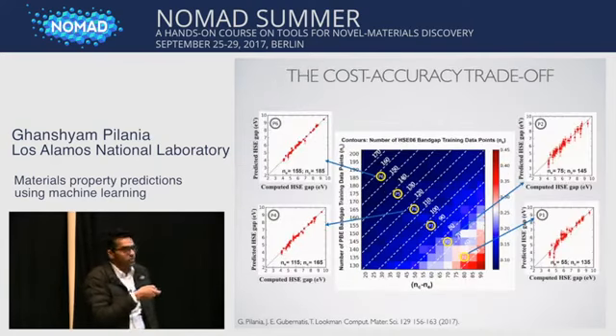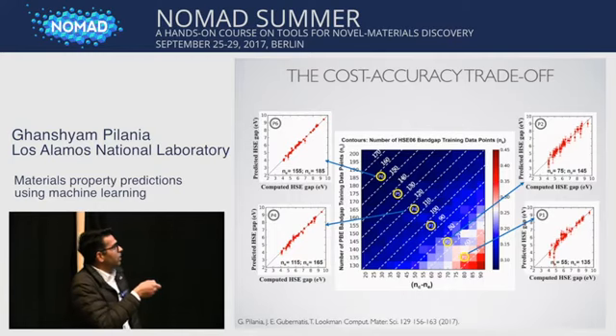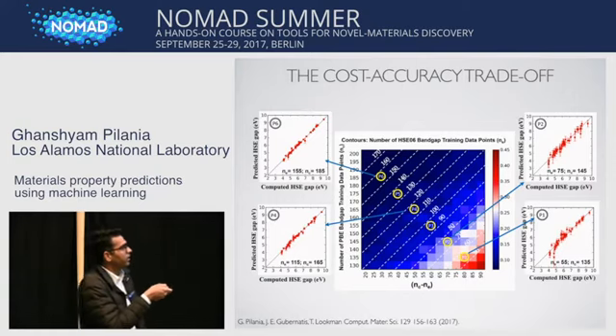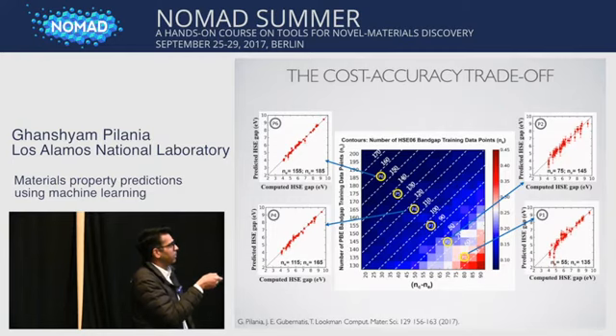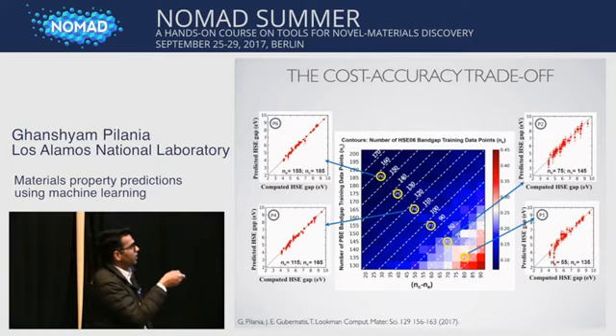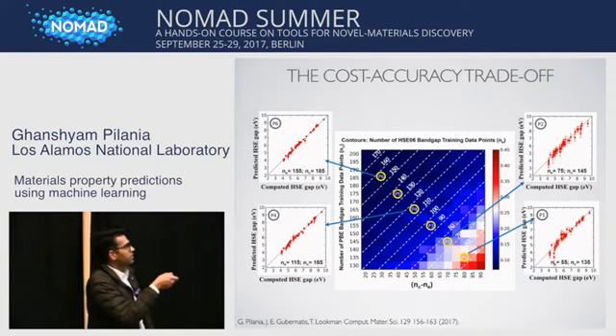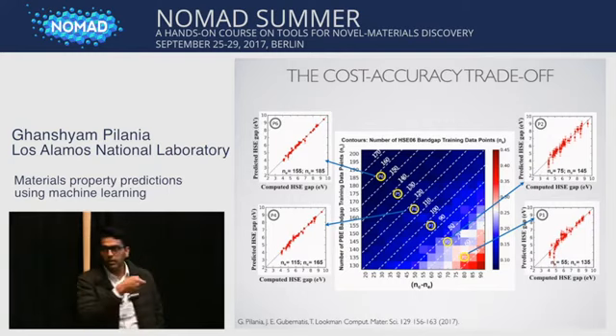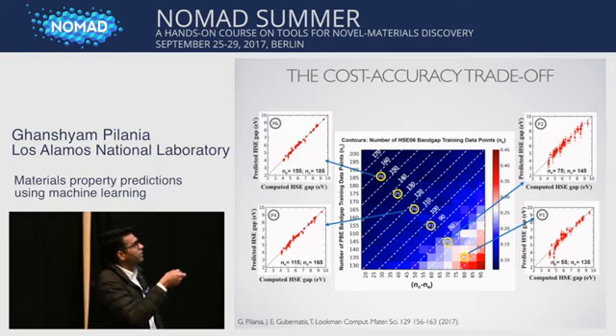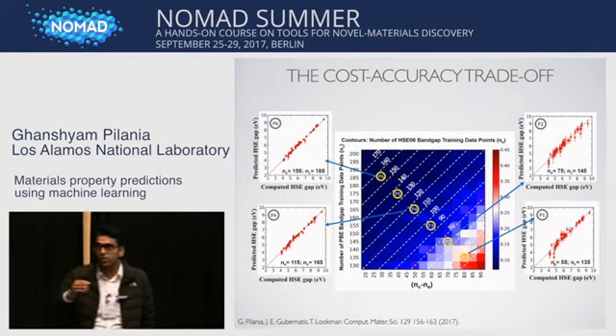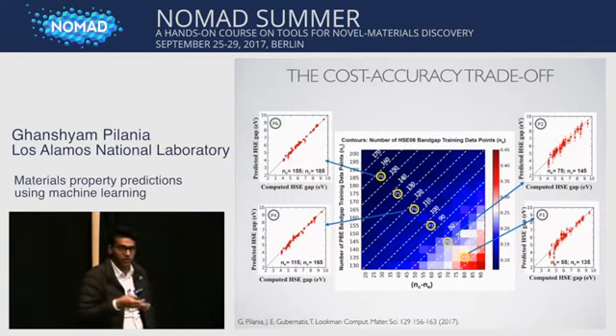Now let's take a closer look at some of the results. So here for selected panels, I have plotted the parity plots between DFT computed HSE band gaps and machine learning predicted HSE band gaps. And as you see, initially when we are at the bottom part of this diagonal, our means are not as good, but also error bars are high. But as we systematically add more data points, not only the means are getting better, that means more and more points lie on the parity line, but also that error bars are shrinking. So the model is making good predictions, but it also has more confidence in those predictions.